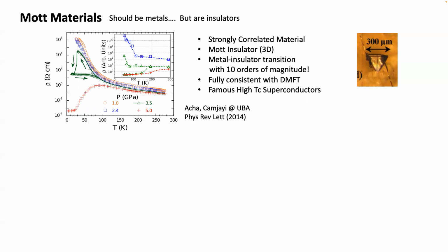It's a chalcogenide material, but you have a beautiful crystal there coming from the lab IMN in Nantes, the group of Laurent Cario and Etienne Janod. And this material, as you see, at room temperature, you can change the pressure and you hardly see any difference. It has just some regular conductivity. But as you lower the temperature, at normal pressure or at low pressure, you see that this material is an insulator with a very high resistance.